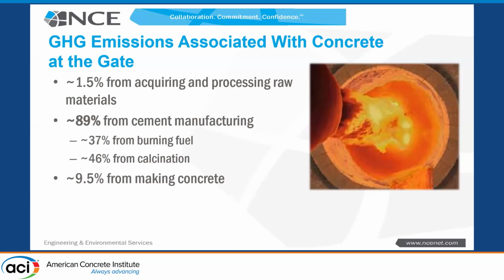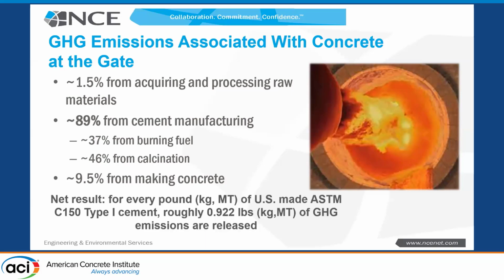But 46%, almost half of the CO2 in that truck, is from taking limestone, calcium carbonate, calcining it, and driving off CO2. All right? The chemical reactions necessary to create Portland cement. And that's really tough to get away from, right? No matter what efficiency we bring into our whole system, that truth stands. So the net result is for about every pound of cement, kilogram, metric ton, take your measure, that we make in the US, roughly 0.922 pounds, kilograms, metric tons of CO2 is generated. A little bit less than one.